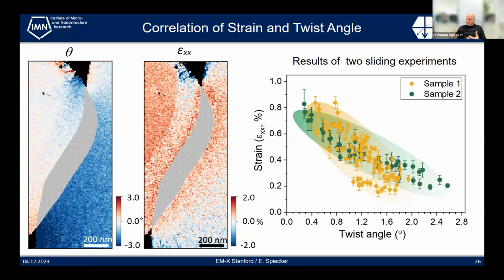And this indicates that the kinetic friction depends on the twist angle, because what we expect if we make a sliding action, and then the two monolayer graphenes suddenly slide, then they arrest again. This is exactly when the strain, which is still present in the monolayer graphene, is compensated by the kinetic friction. This is at least our interpretation.